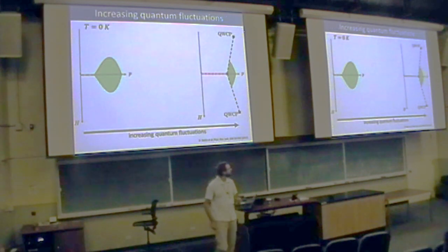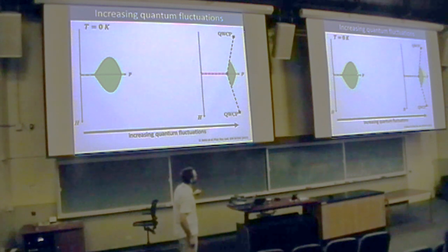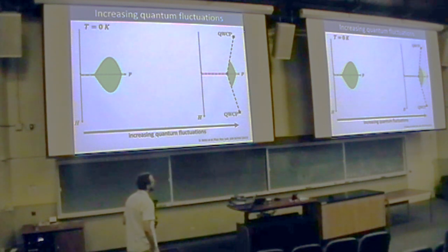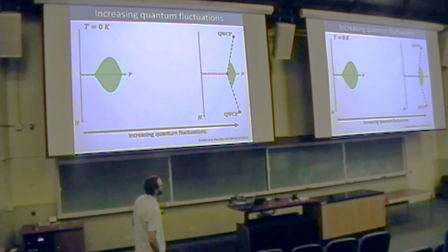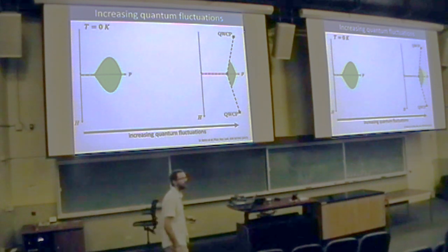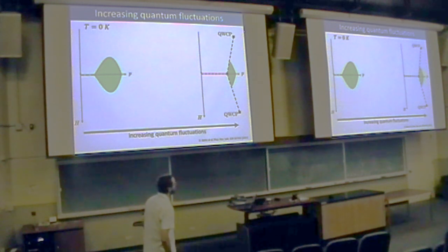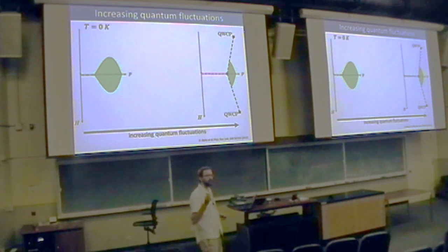So on the left here you have this dome of new magnetic phase region, and again it is symmetric with respect to magnetic field. And for the case on the right, in addition to this region, you have this plane of first order transition that terminates at a quantum wing critical point at high field. And in their theory, they published last year, they were able to show that you can go from one phase diagram to the other when you increase the size of those quantum fluctuations.